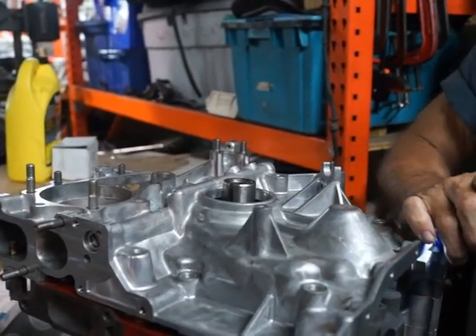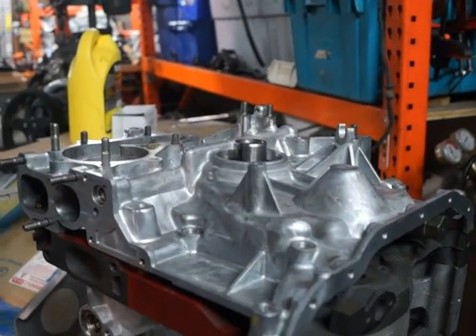That's all controlled by the counterweight? No, it's controlled by the compression ratio. As the rotors became newer and newer, they made them lighter, but they also raised the compression. So the older rotors are heavier. For daily driver gasoline engines, your third generation rotor is more than adequate — it's good to about 15 pounds of boost. Beyond that point they have a tendency to fail; they're quite thin and fairly light. For high power engines, we use the 87 Turbo 2 rotor, which has the lowest compression ratio. We can take them down even lower to run a lot with those engines.